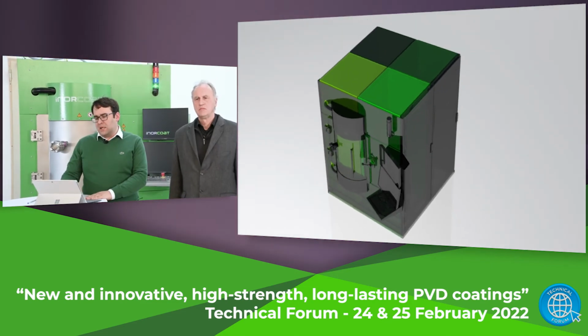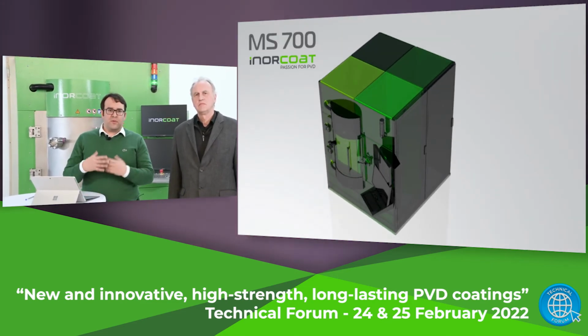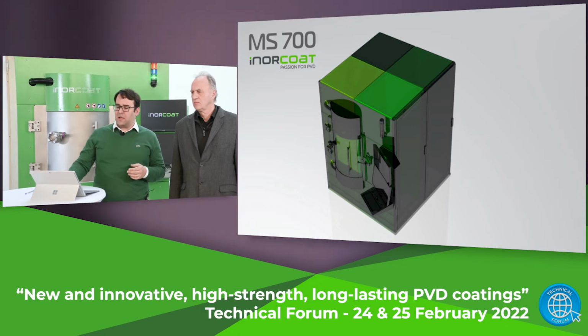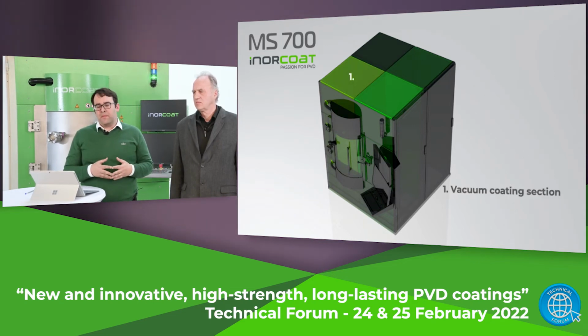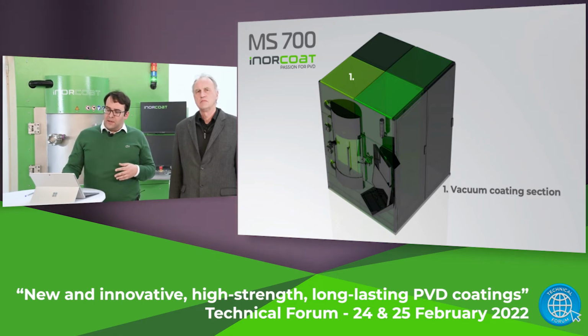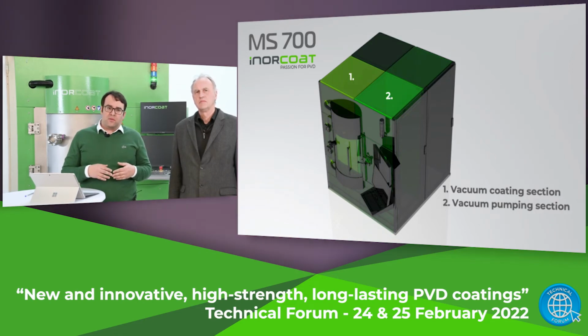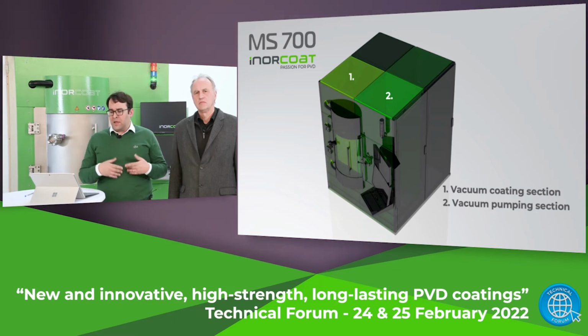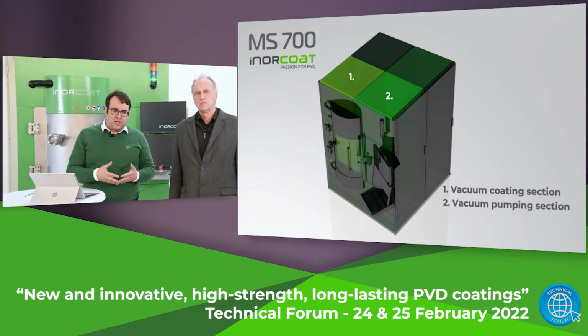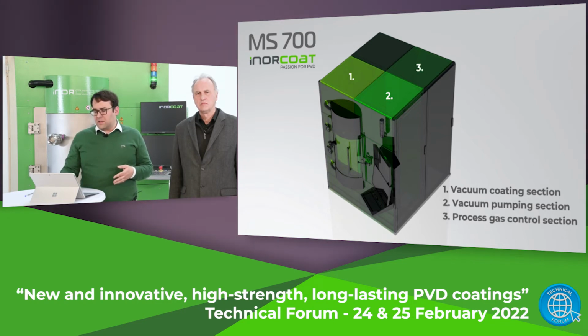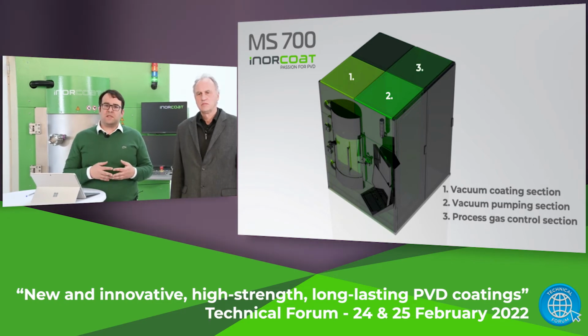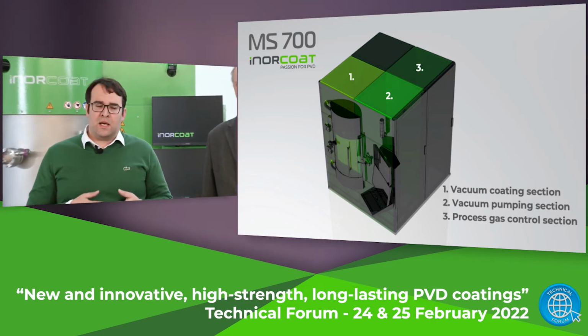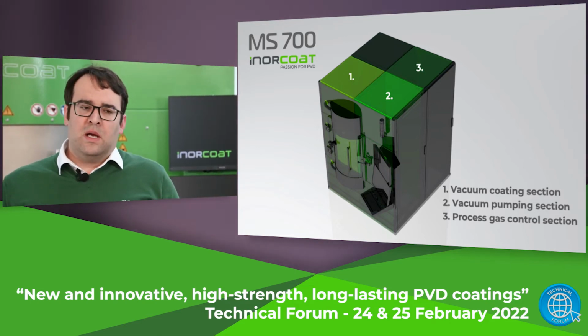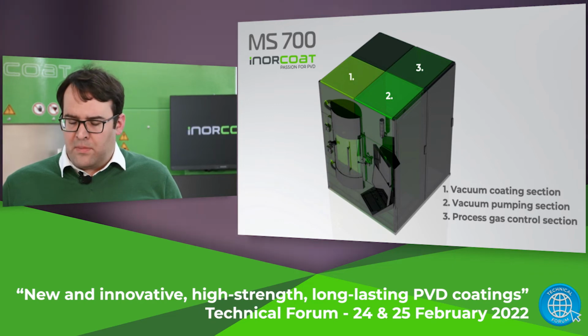As you can see, the machine is divided in 4 segments. We have under segment number 1 the vacuum chamber, where the coating process is actually happening. Under 2, we have the vacuum hydraulics. With vacuum hydraulics, I mean we have the pumping system to achieve the vacuum which is necessary to apply a PVD coating. Under 3, we have the space where the process gases are integrated into the vacuum chamber.